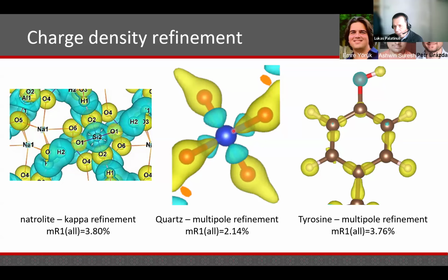And in these 2 images, this shows the so-called multipole refinement, so a full refinement of the deformation of electron density in the crystal due to interatomic effects. And here you can see how the refinement really can determine the shift of the electrons into the covalent bonds, or here the accumulation of electrons around the oxygen atom.